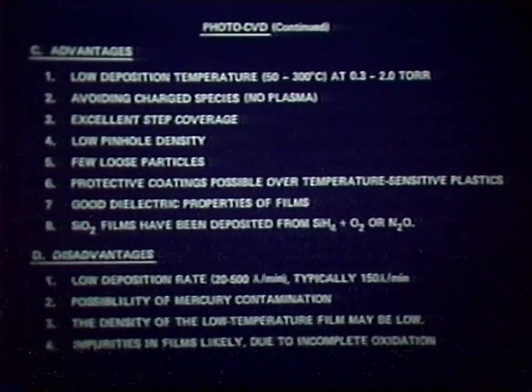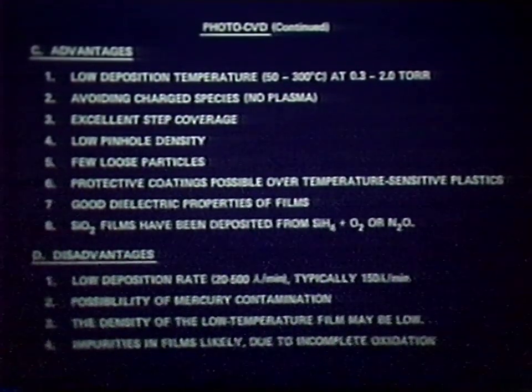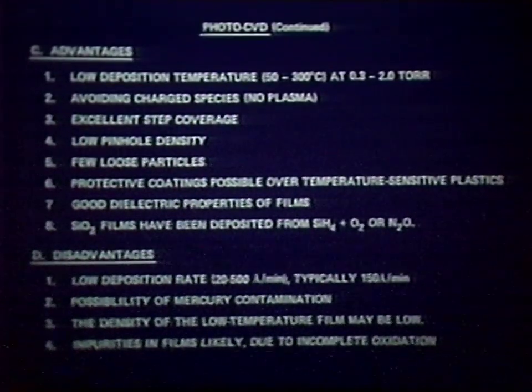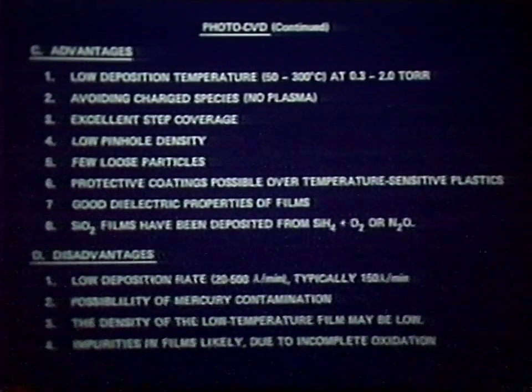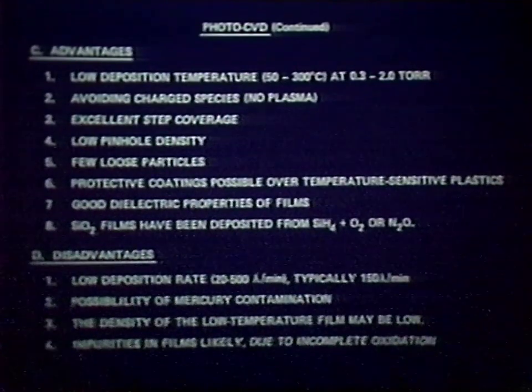Now, the advantages of photo-CVD are listed here. We can use low deposition temperatures, such as 50 to 300 degrees centigrade at a pressure range of 0.3 to 2 torr. We avoid charged species, which is one of the main advantages. In plasma, for example, we do have charged species, that is, we have irradiation effects. We have excellent step coverage that results from photo-CVD, low pinhole density in the films, few loose particles, and so on. And because of the low temperature, we can use this type of process for deposition even over plastic materials, which could not be done readily by any other means.